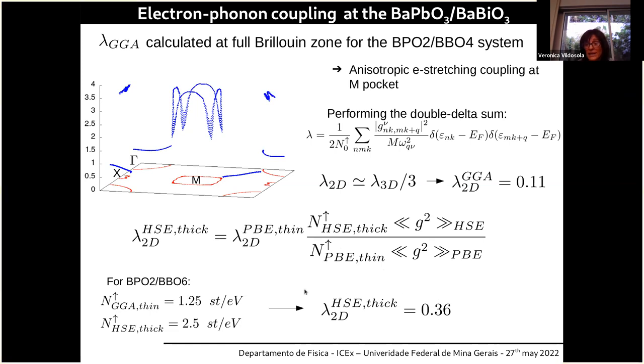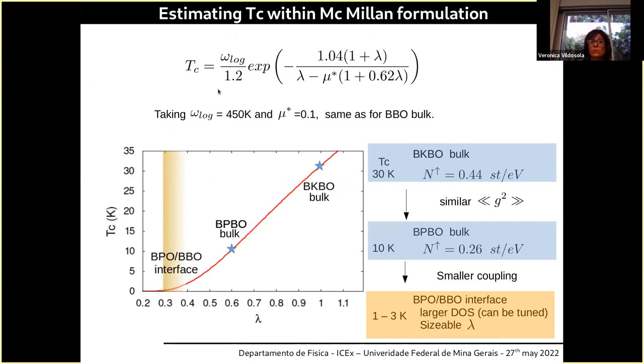And what we get at the end of the day is that the electron-phonon coupling rescaled by hybrid functionals in two dimensions is around 0.36. And with this, we are able to calculate in the McMillan formulation. We were able to estimate, not calculate, because it is a very crude estimation to apply in this formula to obtain Tc, but we are brave enough to do it. And we observe that the frequencies are not varying that much in the interface as compared to the bulk, and neither are these effective parameters that have to do with the electron interactions. And we see the evolution of the Tc according to the McMillan formulation.